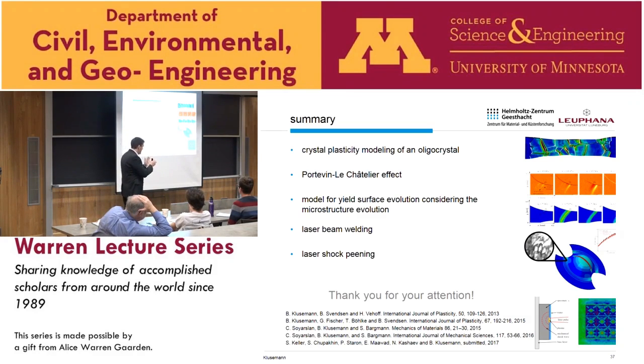No, actually we do modeling, of course, we're not specifically doing the fluid flow, to say that clearly. So we assumed an incompressible element for this, and we of course decrease the properties to a kind of melting stage. So we have a kind of Newtonian fluid at this point, but we still assume, because we're doing finite elements, that it's incompressible, because this was our first problem. We had extremely high deformation in the melting zone, because of no stiffness, if you want to say it so. So for that we needed an incompressible one, and by that we could predict that. But we're not further investigating the melting.